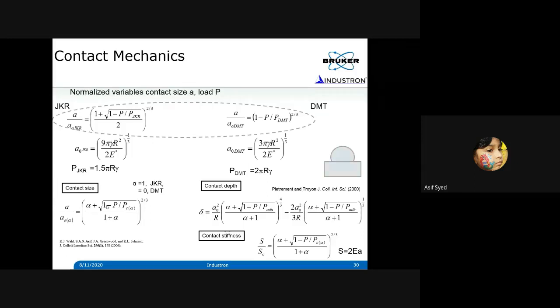The third method is by measuring the contact stiffness. I'm going to present one more way of measuring mechanical properties, that is by force modulation. That was a part of my PhD work which I developed, and you can also use those approaches. So you have three different ways of measuring mechanical properties, essentially the modulus of the material or the surface energy of the material, using three different methods for soft materials.